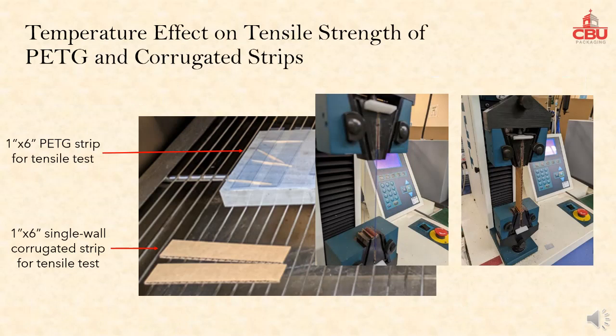Since it was not practical to perform a compression test on PETG specimens, tensile test was used instead. A tensile test was performed on 1 by 6 inches PETG strips, as well as corrugated strips.